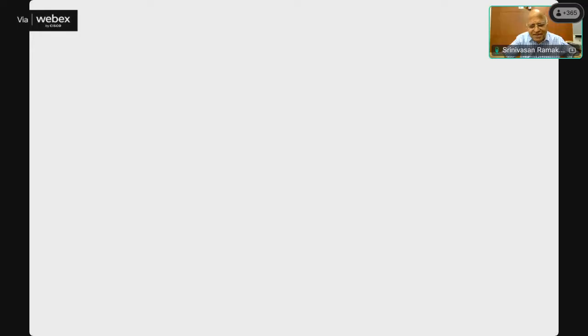You look at a simple metal like tin. It has a very complicated Fermi surface, right? Which we did experimentally find out. So to apply the theory, you need to do a lot more computation. And now, of course, in the last 10 years, the computation has risen to such a level that they can predict this. They can really show the TC of tin is 3.7 K. They can do that. With all this new computation technology, they can clearly show that the TC is 3.7 K from the fundamental theory.